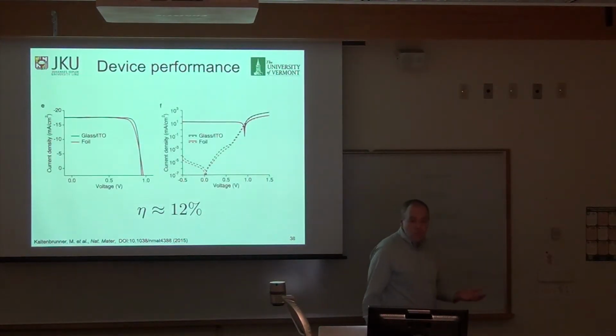So how do the devices work? Well, they work reasonably well. We can get 12% efficiency out of the devices with about 18 milliamps per centimeter squared and a very good fill factor, but a VOC of only 0.9 volts. And there's virtually no difference between those made on glass as to those made on foil, which is good.